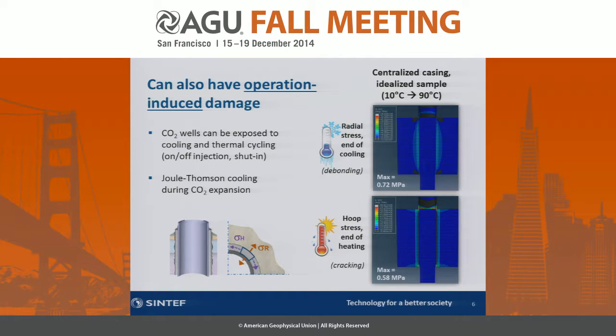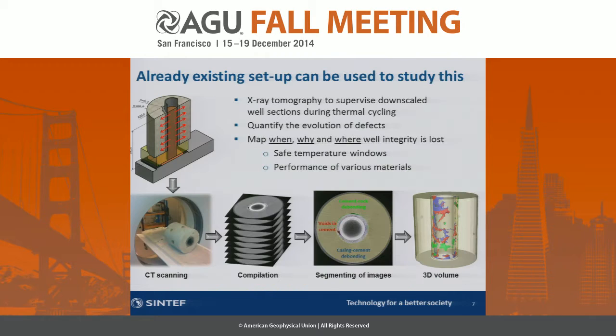So to look into this, we first did some very simplified simulations using Abaqus, where we just exposed a very idealized, centralized sample to temperature variations between 10 and 90 degrees. And what we found was that in this idealized case, we have very low stresses that are building up in the sample, all less than 1 megapascal. But what we were wondering was whether this is actually representative for what is going on in real life.